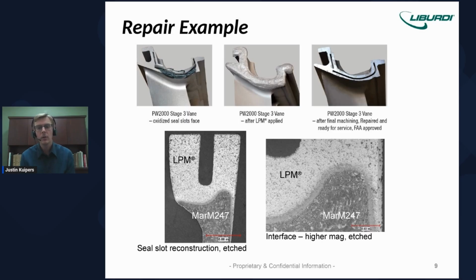We then fill that whole slot and build up material on that side face with our LPM materials. You see at top center an example of a part that's had the LPM putty applied on that surface and has gone through the vacuum furnace heat treatment and been consolidated. And then we do final machining and restore the geometry of the slot on the side of that component. And then it's ready after coating to go back into service again.